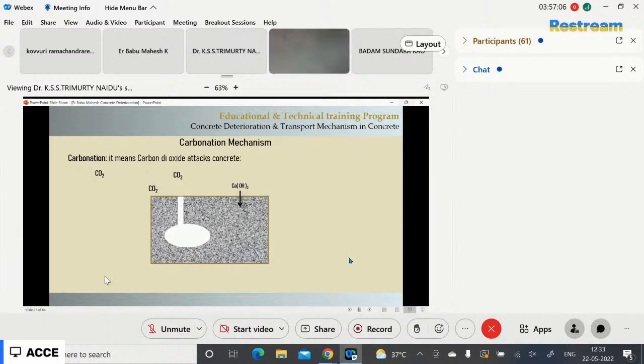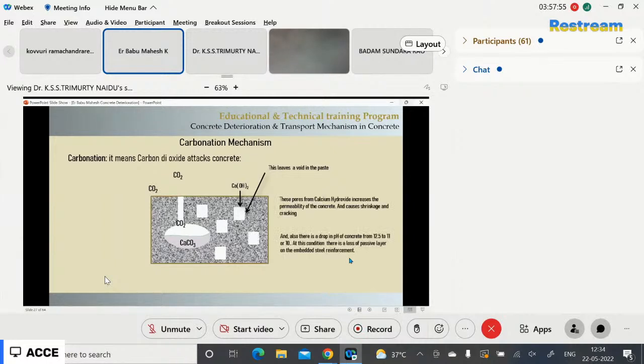Now, the carbonation mechanism. Carbonation means carbon dioxide attacks the concrete. This picture shows concrete having some pores, and those pores are filled with some pore solution. When carbon dioxide diffuses into the concrete, it converts the pore solution to carbonic acid. Again, this carbonic acid reacts with the calcium hydroxide. It forms calcium carbonate, which is an insoluble product.